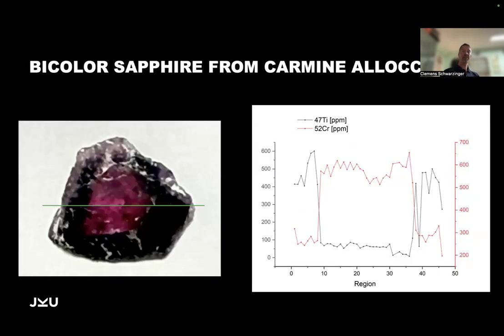I just got a sample last year from, I think, Madagascar, from Carmine Allocco. It's a wonderful sapphire, bicolored. It has a red core and a bluish purplish outside. Again, we measured lots of points from the left to the right, and you can see here I took out just 2 elements. You have titanium, a high concentration at the rim and nothing at the center, and chromium just the other way around. So the red, as we know in corundum, is due to chromium, whereas the bluish color comes from the iron and titanium.